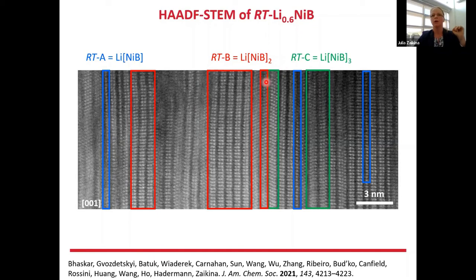And finally, we also see the third fragment, where we have 3 nickel-boron layers stacked together and alternating with a single lithium layer. So upon the deintercalation, we produced a remarkable layered material which has ordered crystalline layers. However, there is no order in the stacking direction. So they stack quite randomly, even though each of these layers is perfectly crystalline.